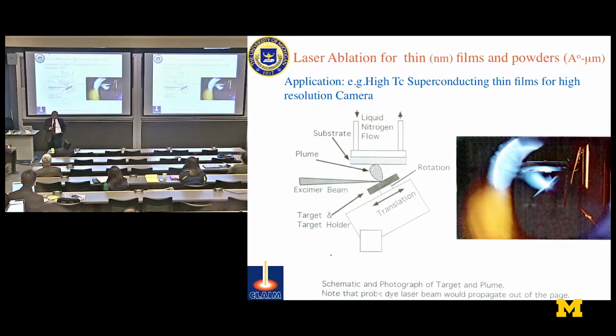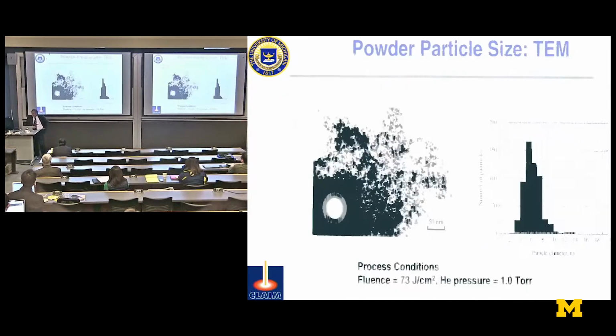I can make a nanocrystalline material out of anything. Okay? And Alan just mentioned that he's increasing the strength of the aluminum casting by putting in nanocrystalline material. So your choice, your portfolio, is increased quite a bit using this technique. Now, am I just saying it? You can see we have made material which is as small as 2 nanometer. One atom is 2.5 angstrom, so the width is about 8 atoms. And the average was 7 to 8 nanometer size by ablating and collecting it.